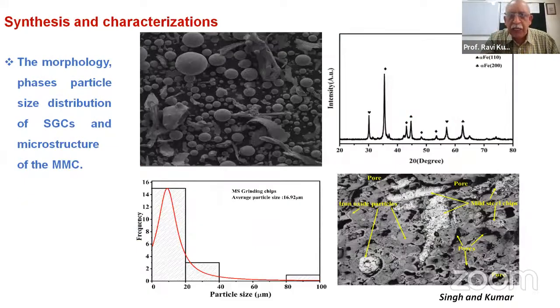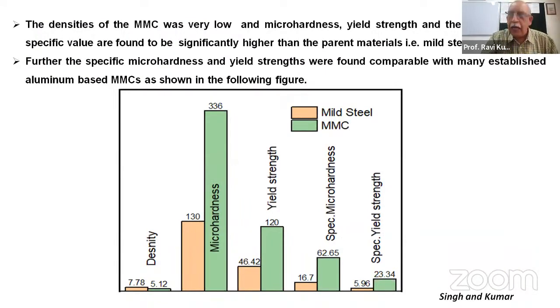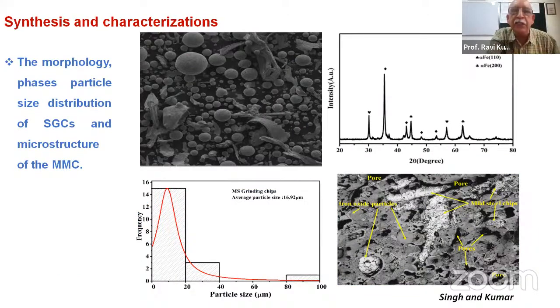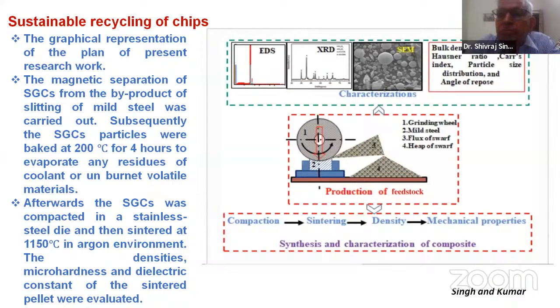Yeah, why not? The work which we have mentioned here is all on pellets. You can see the SEM, this is on a pellet, this is on a powder. We make a pellet, and then we can measure the electric properties, because measuring electric properties on a powder is not possible. Mechanical properties are also not possible without a pellet. So we sinter the pellet at 1150 degrees Celsius in an argon environment, because we don't want further oxidation. As I told you, the formation of the core shell is very tricky, an instantaneous process. If I anneal this in an oxygen or ambient environment, the slow heating and slow cooling will oxidize my whole material. So my purpose of getting the core shell structure is lost.